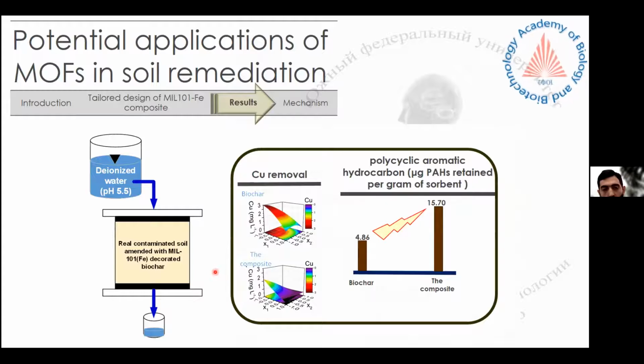It can also activate the low molecular weight polycyclic aromatic hydrocarbons to go to deeper profiles of the soil. Here is the schematic of our column with the real contaminated soil, to which we add different dosages of the MIL composited with biochar. Each day we collect the leachate from the column and analyze the heavy metals and polycyclic aromatic hydrocarbons. Here you can see the 3D graph for the removal of copper. This is the result for biochar, and this is the 3D graph of the composite, showing how the copper has been leached under the different conditions that we had. The first concentration we saw started from 3, but for the composite it's almost 1.5. So it's like a half decrease.